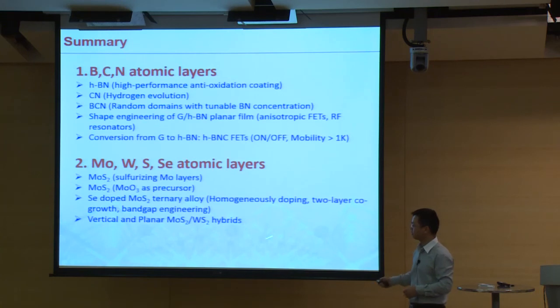And the second part is the moly, tungsten, selenium, sulfur system. In this big family, we can make high quality moly disulfide. We can dope the selenium into this system to get homogeneous ternary 2D layers. And we can also make some vertical and planar hybrids.